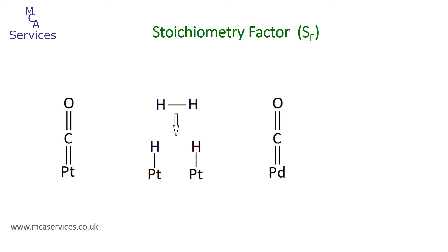There are some special cases where things get a little bit more complicated. One good example is carbon monoxide chemisorption onto palladium. This can form a linear one-to-one bond with a stoichiometry factor of one, and also a bridged bond with a stoichiometry factor of two. In this case, for CO adsorption to palladium, it's quite common to assume a stoichiometry factor of 1.5.